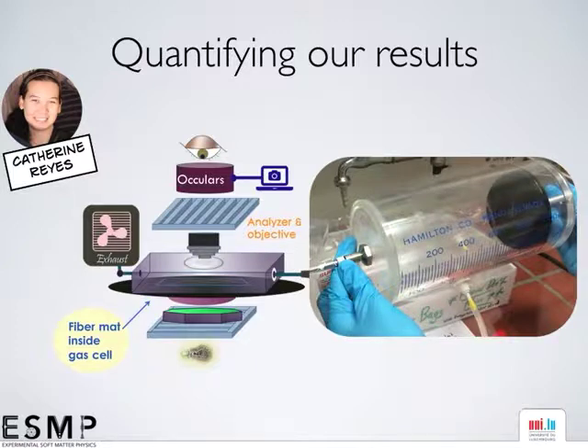The reason that she's using this is that it's a good way of preparing toluene vapor with controlled concentration: you simply take a large volume of air, take an Eppendorf pipette and dispense about a microliter of toluene, close the syringe and let the toluene evaporate. Then you know how much toluene you have in the air. Now, as I will tell you in a moment, it turned out that it wasn't quite as good as we hoped, because this syringe here is polycarbonate.